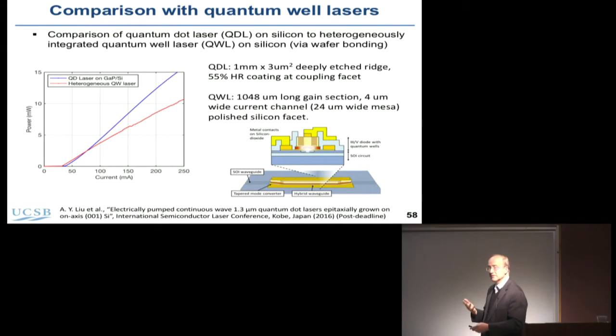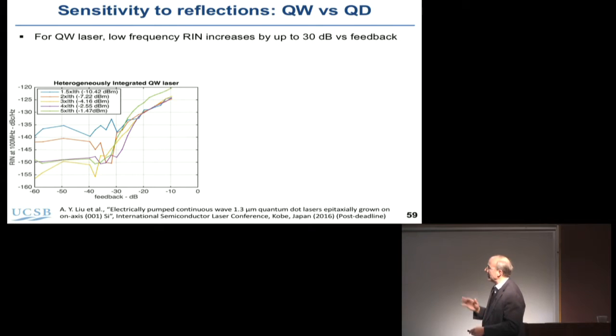So we did a comparison. So these are all quantum well lasers on silicon, quantum dot lasers on silicon. They're not perfectly equivalent, but they're not too far off. And so what you see here, this is a quantum well laser on silicon. And so this is the RIN, the relative intensity noise of the laser. And up to some level of feedback, about 1 part in 1,000, everything's OK. But then things get bad in a hurry. So lasers becoming sensitive to reflections. There's noise. It's not usable. You need an isolator if you're going to be in this region.